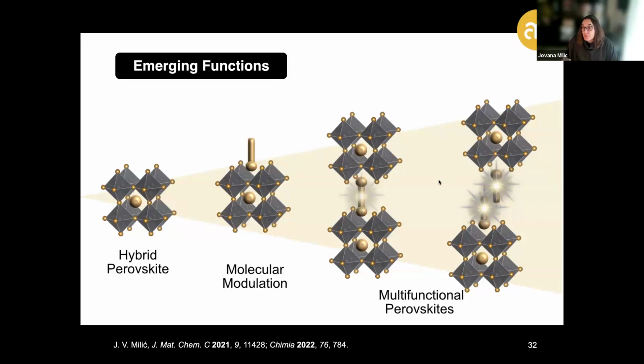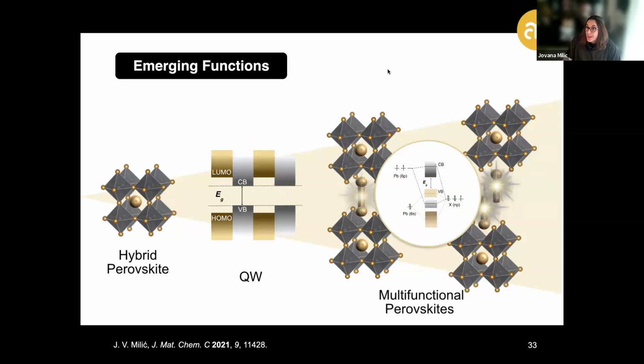In general, the systems I previously outlined, with their corresponding organic spacers, primarily involve electronically inactive or insulating organic components, causing these systems to behave as natural quantum wells, as optoelectronic characteristics are primarily defined by metal halide orbital overlaps that define properties including band gap, while the organic component serves more a structure templating role without direct contribution, leading charges to be confined to the inorganic layer, while the organic system merely indirectly controls the resulting structure and properties, which can be further tailored by introducing other organic systems with complementary, more electroactive characteristics.